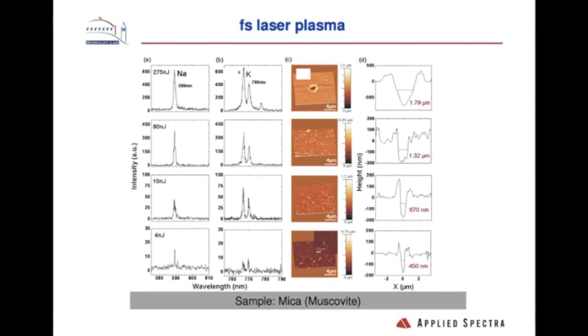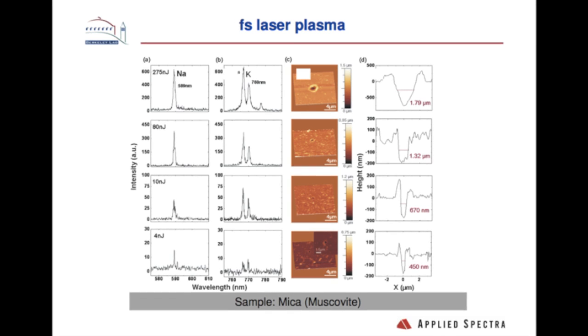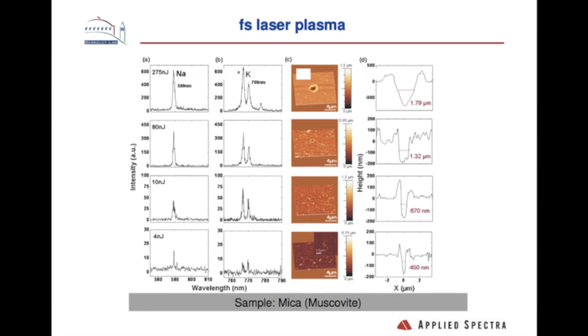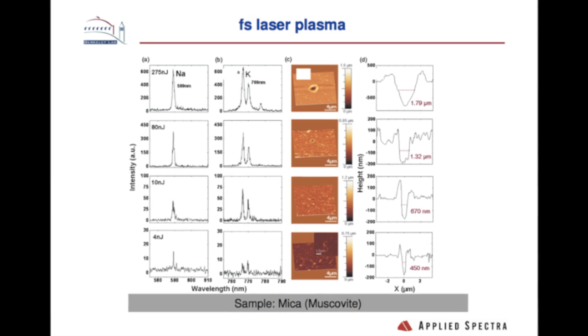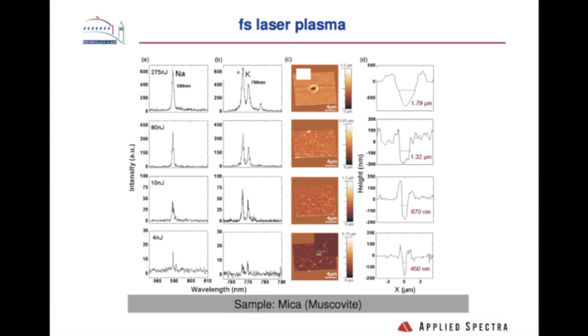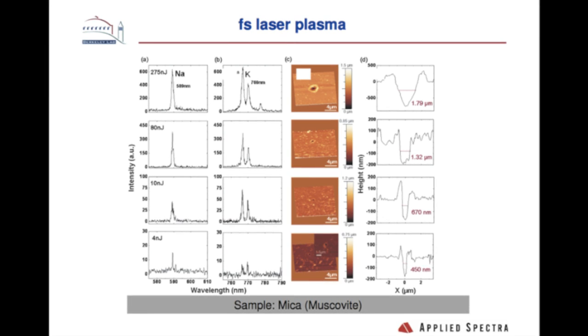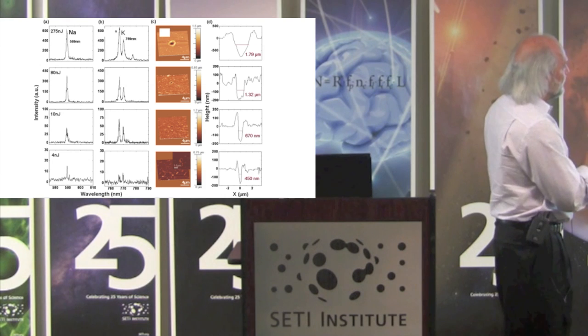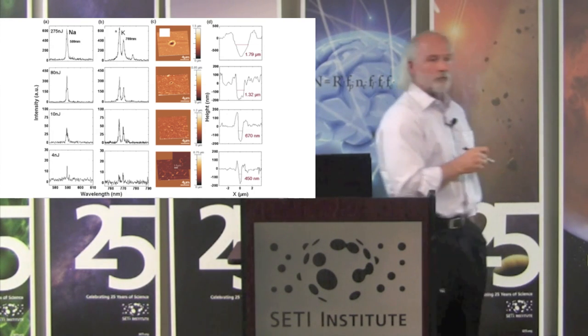And what this represents is just the spot size that we ablated. So this would be the surface, this would be the crater that the laser caused. And you can see the crater size in the sample. These are AFM images. And you can see the atomic spectroscopy. So we're only using 4 nanojoules of energy from our laser.